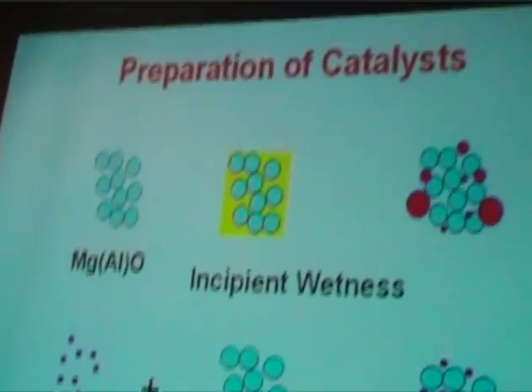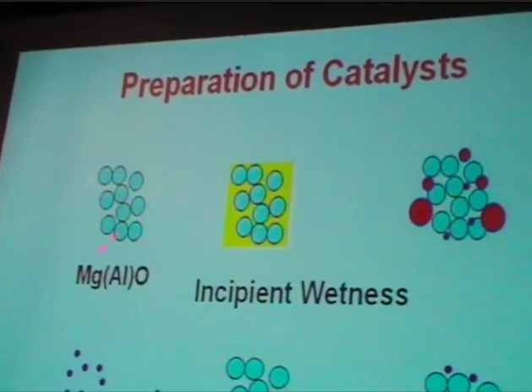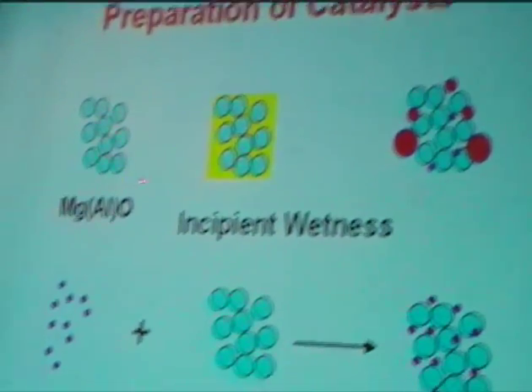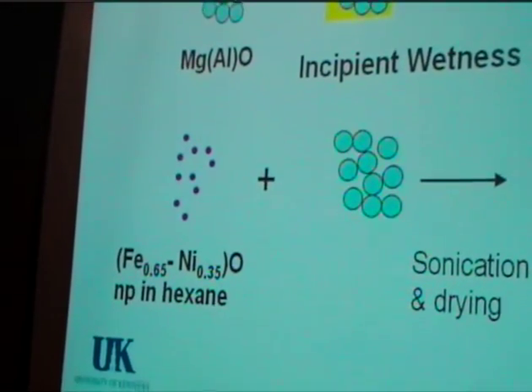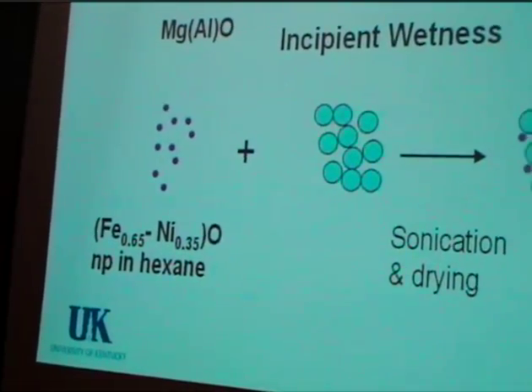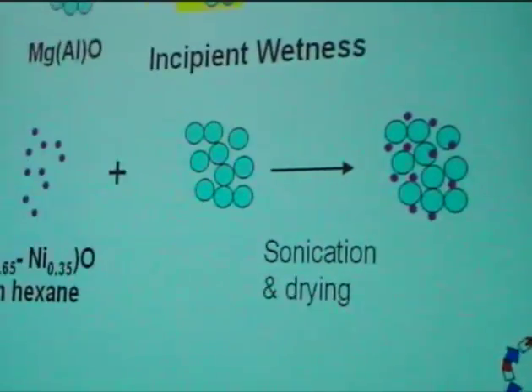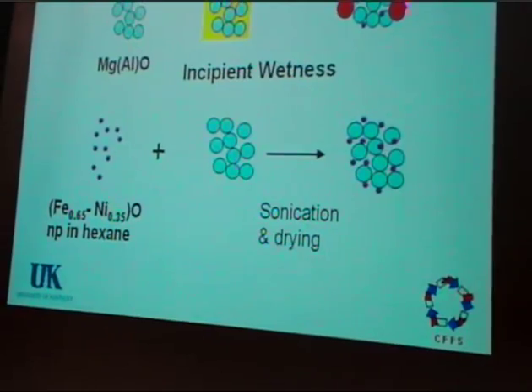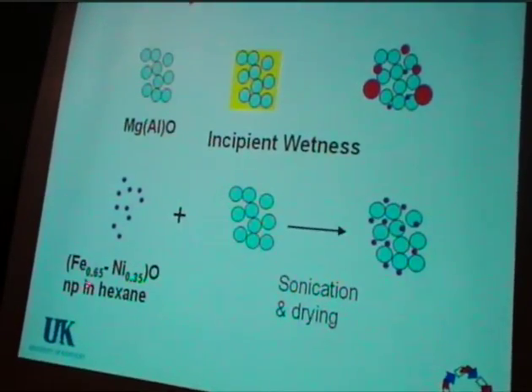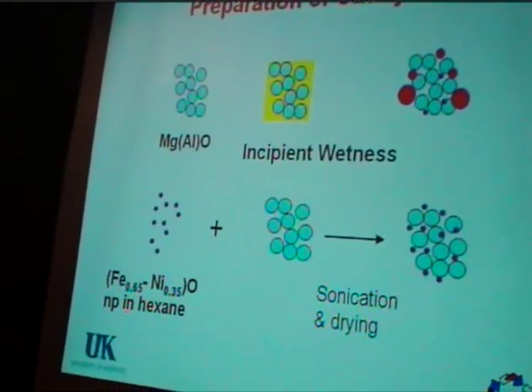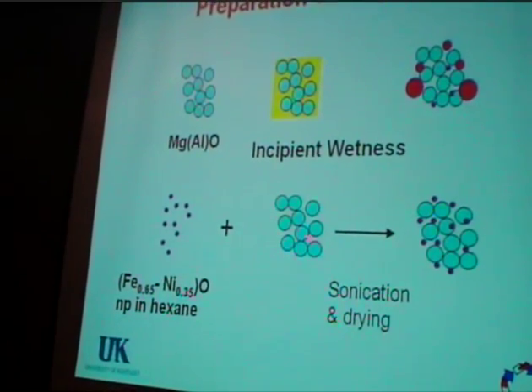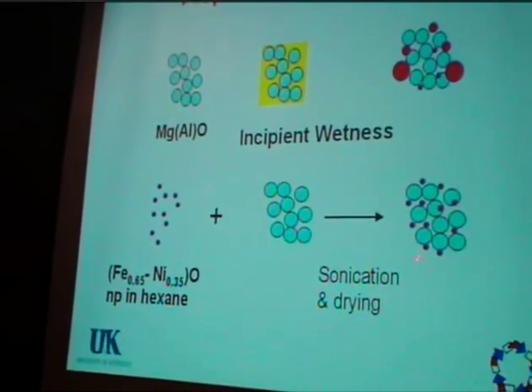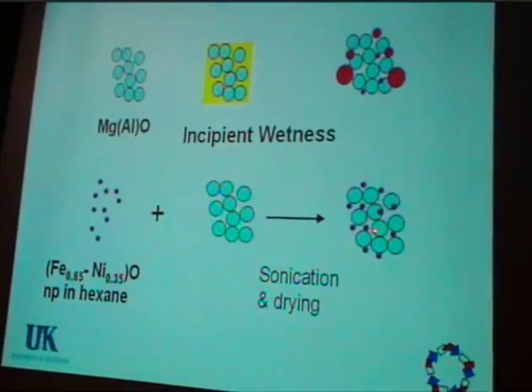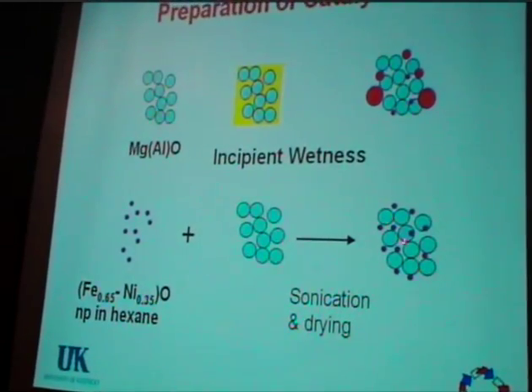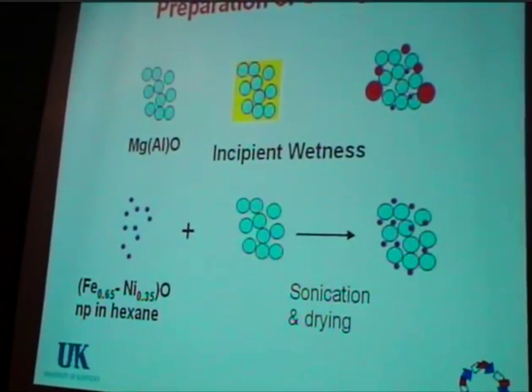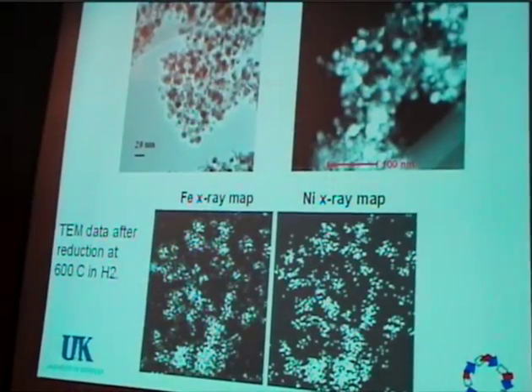So to prepare the catalyst, we take the magnesia alumina support, and those particles actually are pretty small too. They're in the 20 to 40 nanometer range. And if you do it by incipient wetness, of course, again, a range of particle sizes. If you disperse your nanoparticles in hexane, you can use sonication and drying to produce a fairly uniform dispersion of the iron nickel nanoparticles on the magnesia support.